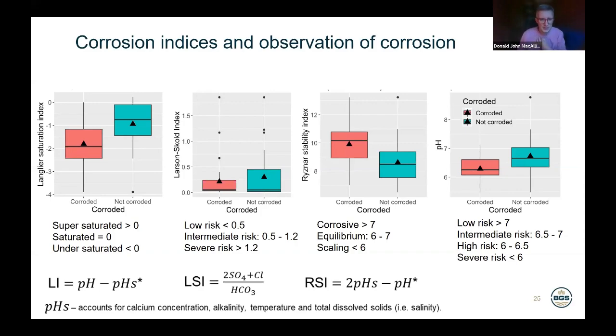So you can see for the first three, the Langelier, the Larson-Skold, and the Ryznar stability index, at all the sites, when we calculated these indicators, all the sites were in the risk area for corrosion. For example, for the Larson-Skold indicator, there wasn't really much difference between our observations of corroded or not corroded. So these indicators are telling us something, but the main thing they're telling us is that at all these sites, we're at risk of corrosion.